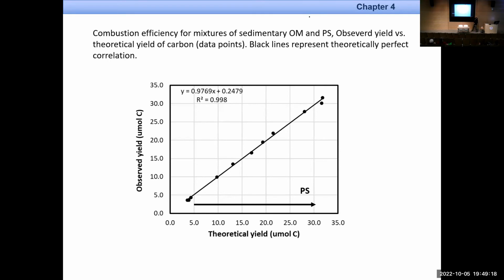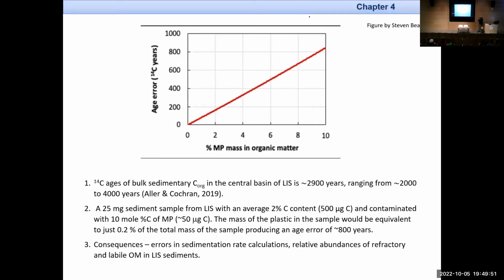So that line here with the black dots is telling me that the equipment is burning the plastic together with the POC. So I cannot distinguish. If I have plastic in my sample, I cannot distinguish the carbon from the plastic from the carbon from the natural samples. So that is a problem. Or that could be a problem, because now I need to see if we really are capturing plastic with our carbon measurement.